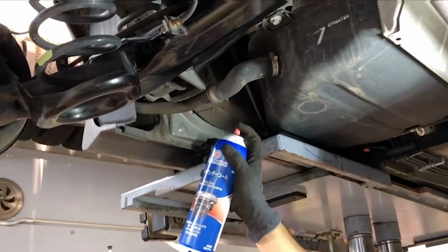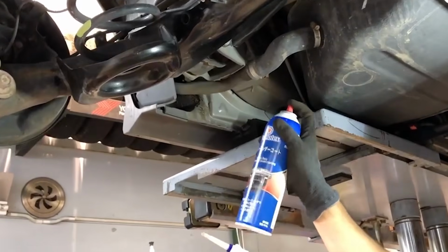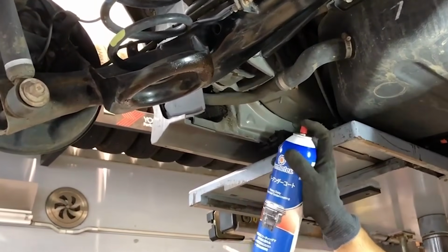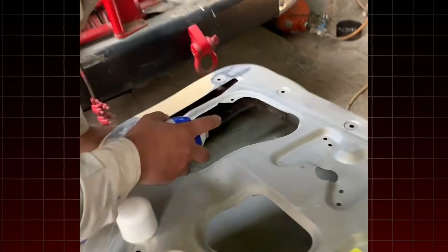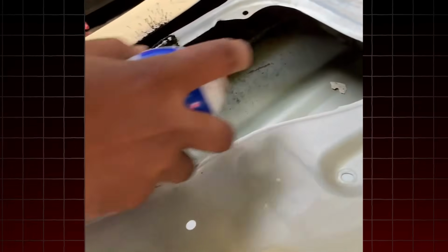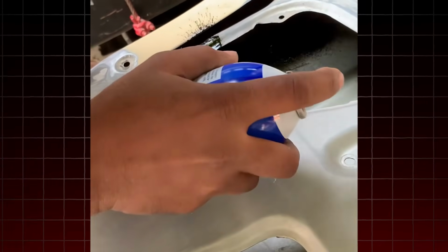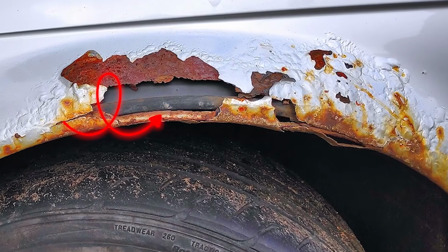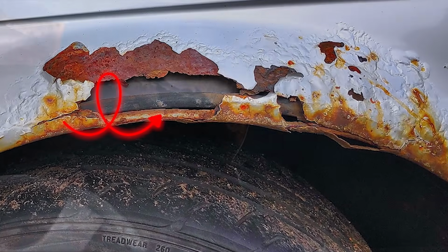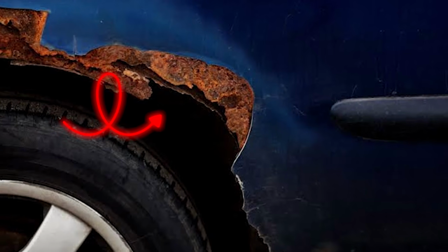The limitations appeared at the 90-day mark of winter exposure, specifically in areas where the application coat was thinner than the recommended wet film thickness. The higher molecular weight formula showed a specific failure pattern there. The film contracted slightly during sustained cold exposure. This contraction produced tension cracks at application edges, where the coating transitioned from the treated area to untreated metal. These tension cracks allowed capillary moisture penetration at the exact boundary where undercoating protection matters most.